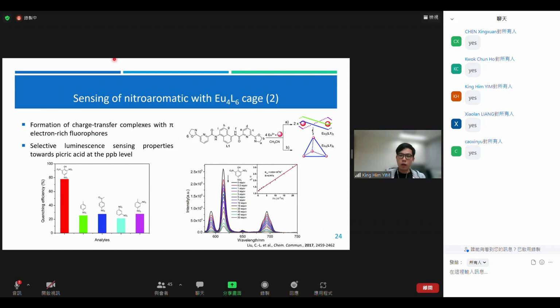And then after confirming the structure of this Eu cage, they tried some sensing of nitroaromatic compounds. They put 5 different explosive nitroaromatics in, mixing them with the cage. And they found that there is a selective luminescence quenching for picric acid at the ppb level. What they claim is that the electron-deficient nitroaromatic probably forms a charge transfer complex with the pi electron-rich fluorophore, which quenches the overall luminescence. On the left-hand side, you see picric acid exhibits a quenching efficiency of around 80%, while the others just got 20%. And on the right-hand side, it shows the emission spectrum, where upon the addition of picric acid, you can see the emission intensity drop.